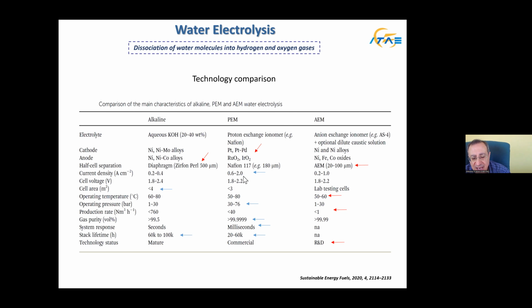So operating at high current density, we increase the production capacity because you know very well the Faraday law. The Faraday law correlates current with reaction rate. According to the Faraday law, the current density corresponds to the reaction rate. So if we increase the reaction rate, we increase the production capacity and we can minimize precious metal electrocatalysts. Other relevant advantages are high purity for hydrogen, good dynamic behavior, high pressure.